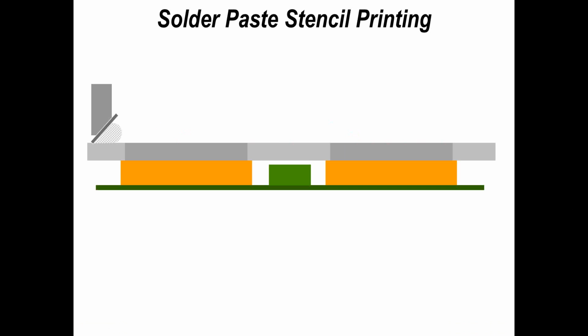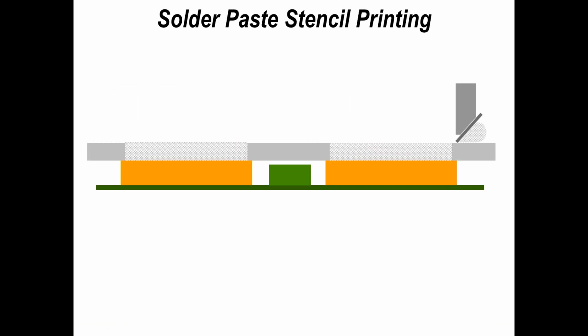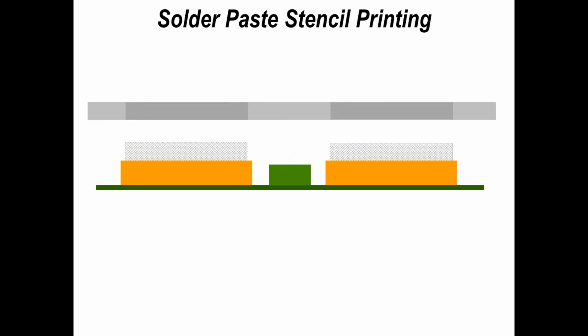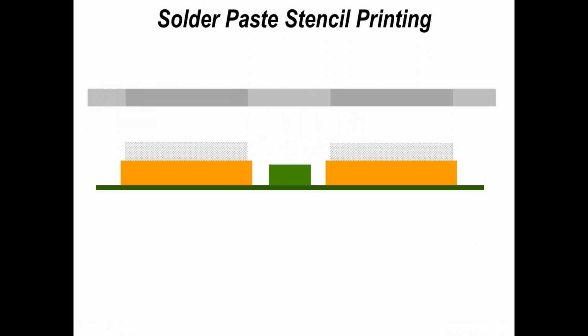Now, when we look at the printing process, the key thing is making sure that all surfaces are flat and even to get the best print deposit. And here we see just an example of a stencil printing process where we're printing paste onto the surface of the printed circuit board. And then we separate the squeegee blade from the surface of the stencil, and then we lift the stencil off of the surface of the board, leaving the solder paste deposit on the surface.